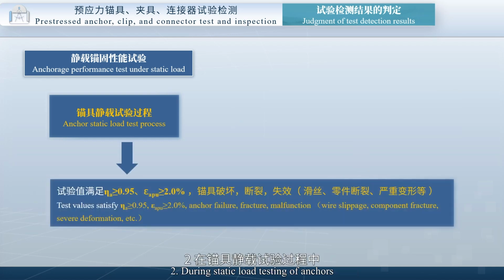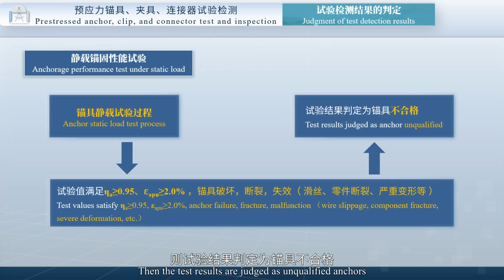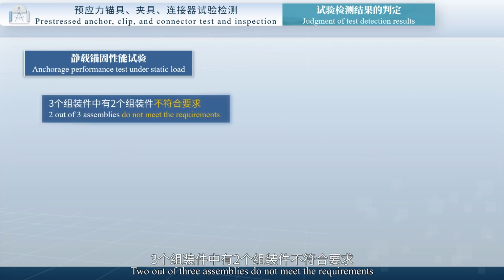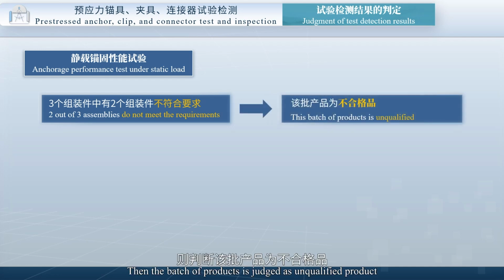Second, during static load testing of anchors, although test values meet eta A greater than or equal to 0.95 and epsilon APU greater than or equal to 2%, when the anchor fails due to fracture, the test results are judged as unqualified anchors. If 2 out of 3 assemblies do not meet the requirements, then the batch of products is judged as unqualified.